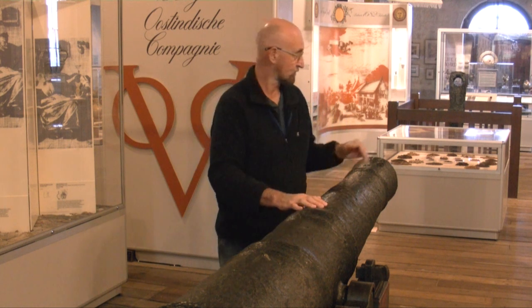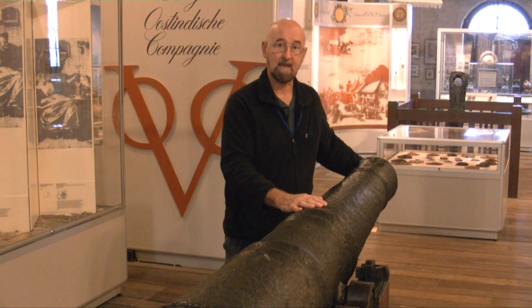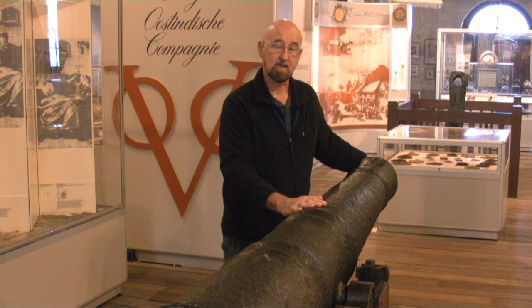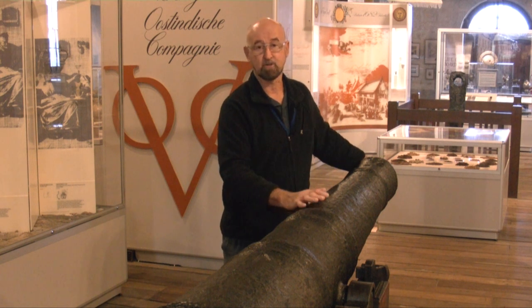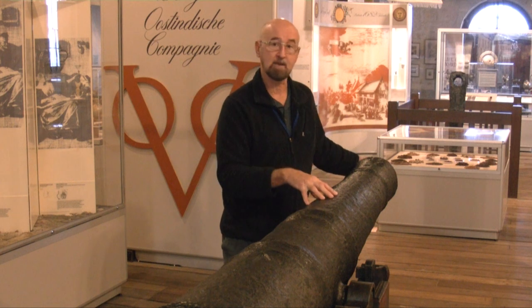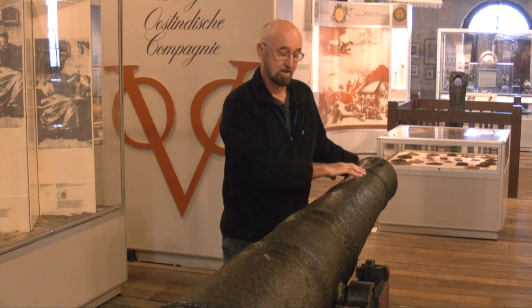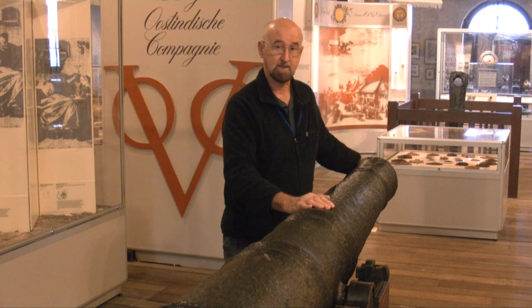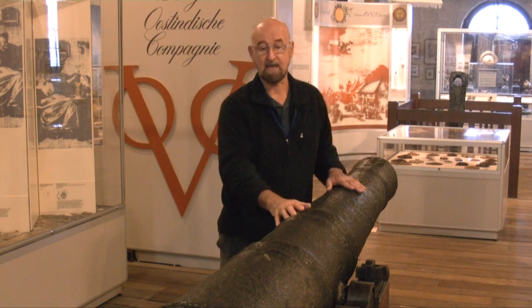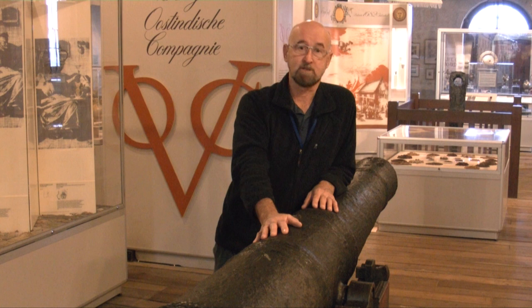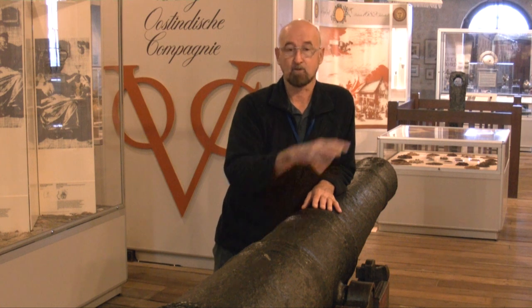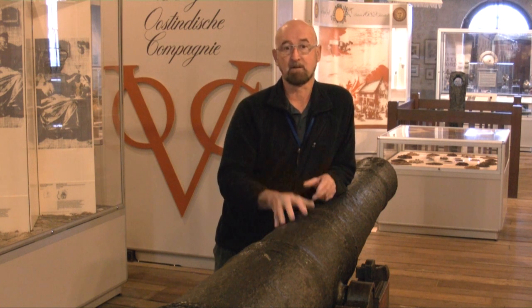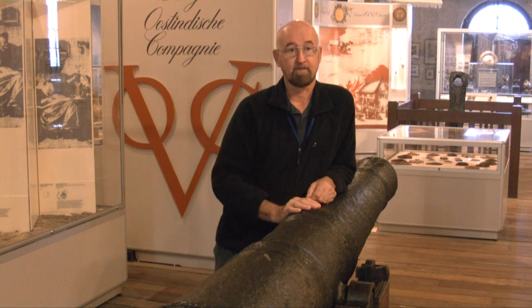Sometimes that concretion also forms inside the bore of the cannon. And if we're lucky enough to have a plug called a tampion or a tompion, which is a wooden plug in the end, and that survives, then the concretion doesn't form inside, and that means it's clear. This particular cannon still had its cannonball inside. It had the tampion or the plug at the end. It had the wadding, and we were able to remove all of that successfully.